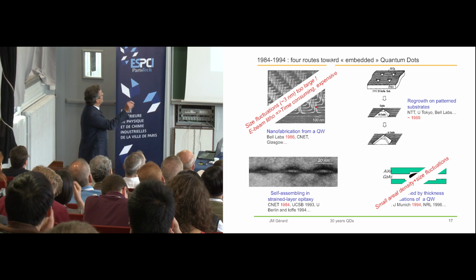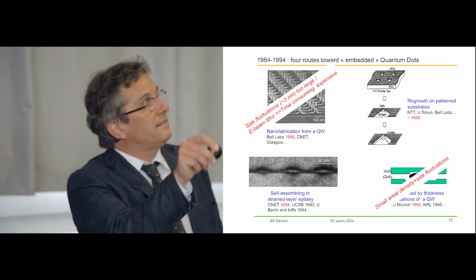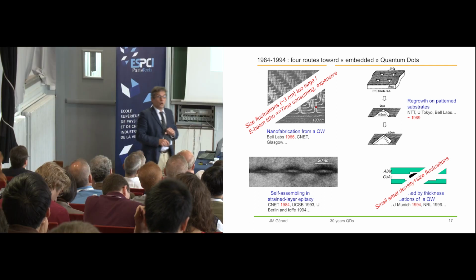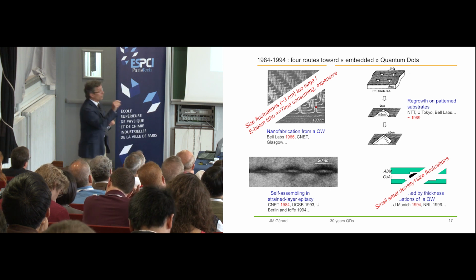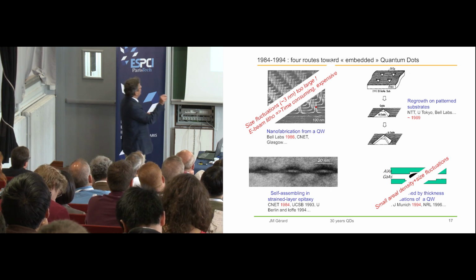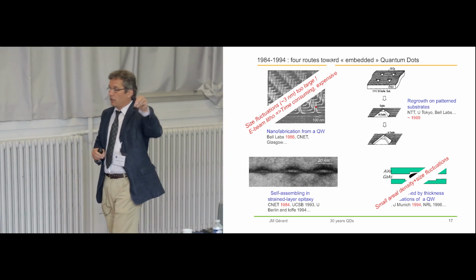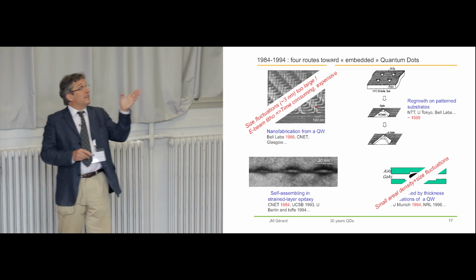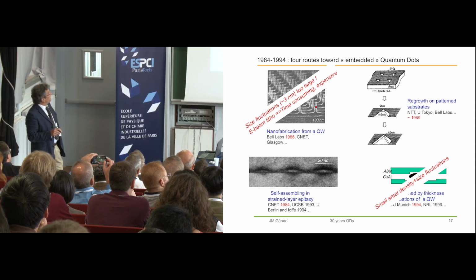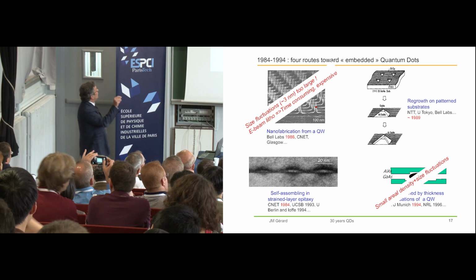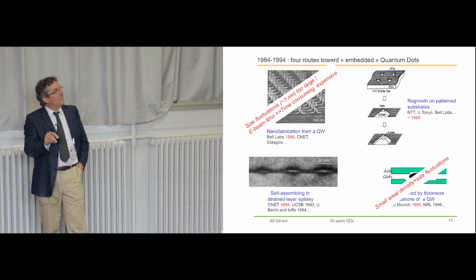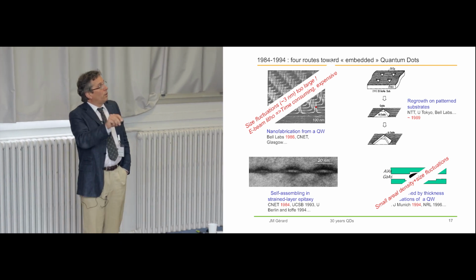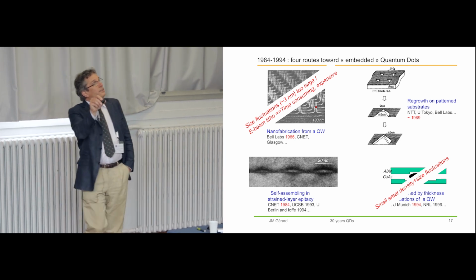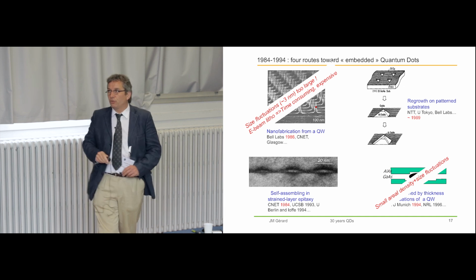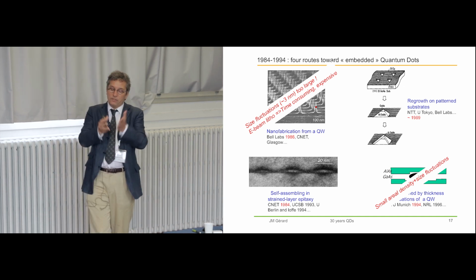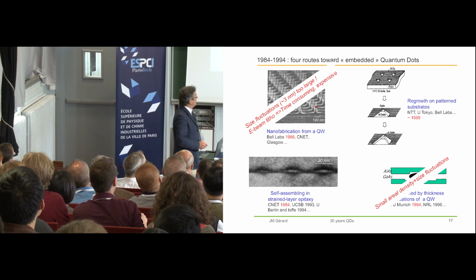People had played a lot with nanofabrication. Here you have, for instance, arrays of quantum dots etched from a quantum well. In the end, they were able to get light from such dots. However, the size distributions induced by nanofabrication were not good enough, typically 3 nanometer fluctuations in the dimensions. And also, it was extremely time-consuming and expensive. Other approaches were the self-assembling in strain layer epitaxy, and also the growth on patterned substrates. It can be the growth on top of pyramids, or the growth at the bottom of V-grooves, as shown by Eli Kapon, for instance.